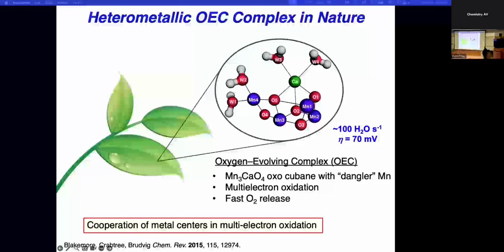Now, if we look again to nature, what we see is that nature pulls off this reaction with a very interesting inorganic reactive site. And that active site has 4 manganese and a calcium positioned in the manner that you see here. So 4 of the metals form kind of what we call a cubane. They're bridged by oxygens. And this is a very efficient catalytic system. Very fast. The overpotential is really incredibly low, about 70 millivolts.